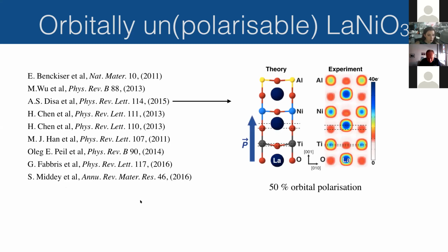But still, I believe the highest orbital polarization that was ever achieved was achieved in a tri-layer structure. So now they've inserted a layer of titanate as well as the nickelate and the aluminate. The highest was 50%, which is good, and it's a really super impressive study, strongly guided by theory, but it's not enough. It's not 100%. So these structures are all insulating in the end.